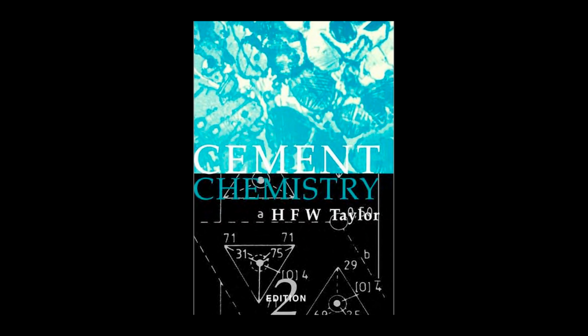At high temperatures and high humidities, the initially formed hydrate, CAH10, converts into denser, more stable phases, C3AH6 and AH3. And this phase conversion increases the total porosity of the concrete and reduces compressive strength. So why are they still used? Because of the chemical protection. Despite the internal strength reduction, the conversion often forms an extremely hard, non-porous surface zone that restricts the penetration of external agents. So this paradoxically provides excellent long-term chemical durability, even if the internal bulk strength drops somewhat.